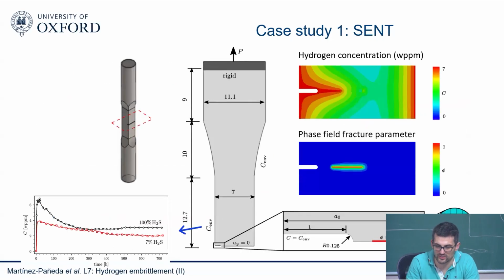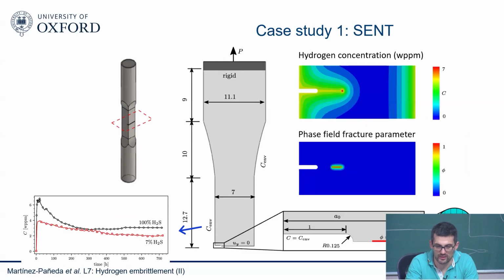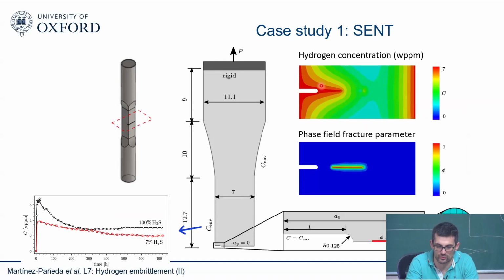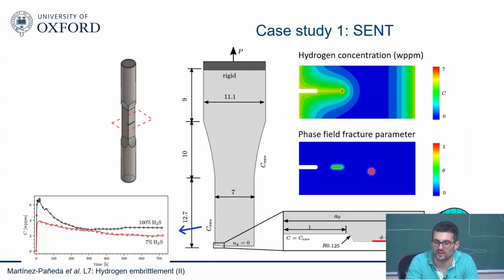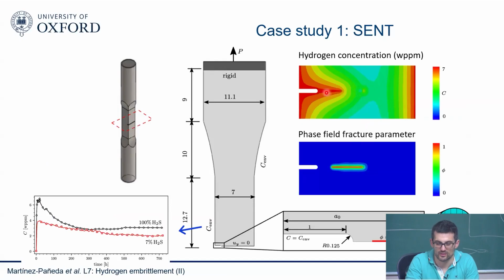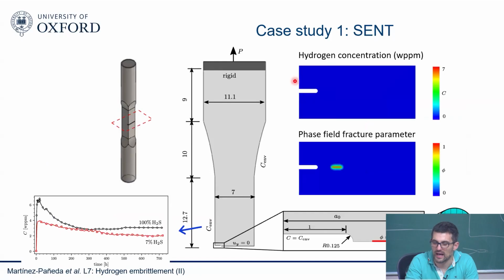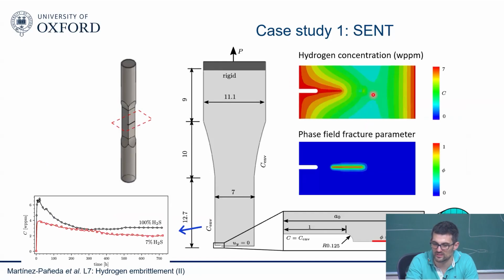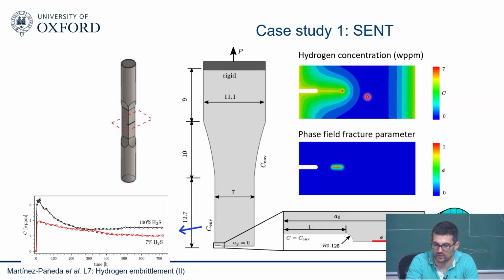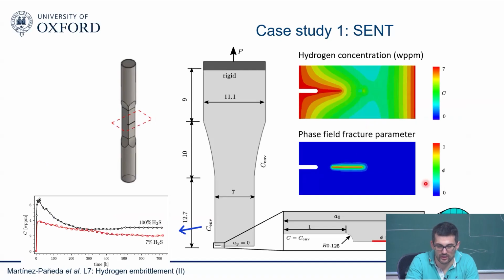So this is the kind of test that we do. You see here is a constant load test, so eventually you see your crack growing, and at some point your crack stops. So this is what you measure. So this is the hydrogen concentration. Again, it's important to capture how the hydrogen concentration follows the crack. You can see that it's happening there. So this is the crack growth. This is the hydrogen concentration. And this is a 2D boundary value problem.